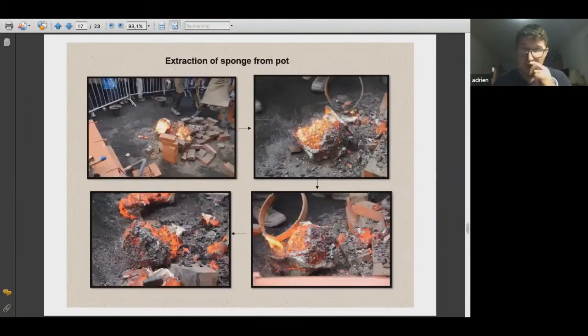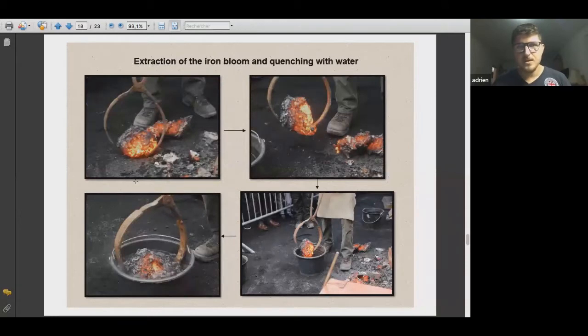One of my pieces of advice also is to clean it. All has to be clean when it's hot, because when it's going to be cooled down, it's going to be very hard to knock it out from the bloom. So if you keep it for a museum, okay, you can leave it like this if your museum wants this. But if you want to forge it, clean all the outside with an iron stick before putting it in the water. So we clean it, and you see it on the second photo here, it's only the bloom, and we put it in water.